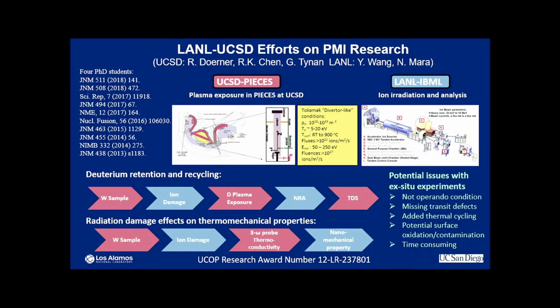So quickly, so far all the experiments have been done ex situ. We do the irradiation, we send the sample to other places to do the plasma exposure, then we get the sample back to do the analysis. And there are many issues happening during that cycling process. You have to vent your chamber, change the temperature, surface contamination. Also, some of the short-lived defects may not survive during that process. So it does not capture the whole picture there.